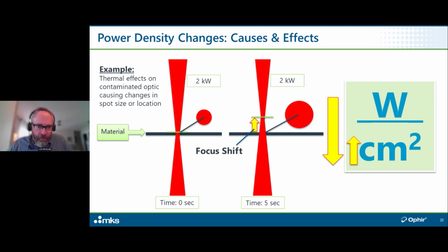Let's move to the bottom of the equation, and I want to illustrate this point. Same laser. You've got 2 kilowatts being programmed. You've got it processing some material. And when the laser turns on, everything is fine, but you've got some kind of thermal effect on a contaminated optic that's causing some spot size change or location. So you've got a spot size that it's intended to be when you start off, and then some seconds later, 5-10 seconds later, you've got some kind of focus shift on your laser system. What's happening at the process? At the process, the laser spot size is increasing. Well, using simple math, if your denominator increases, what does that do to the overall expression? It decreases the overall power density in this case.